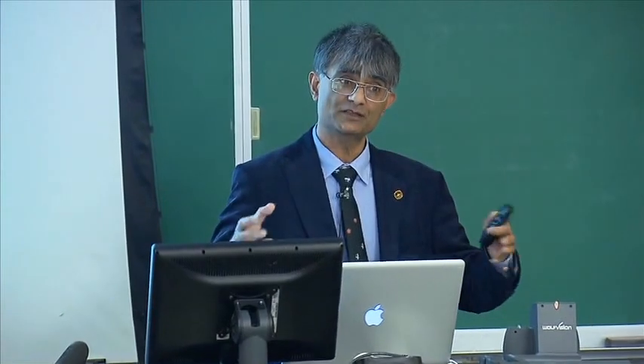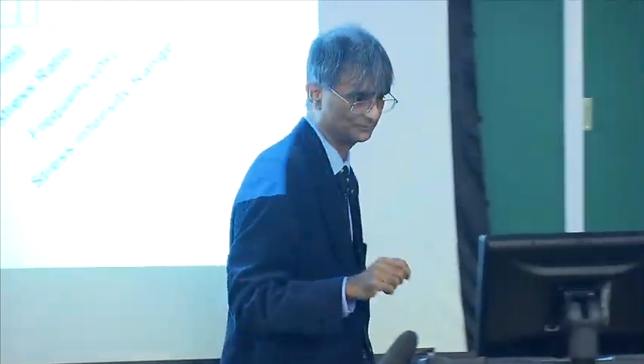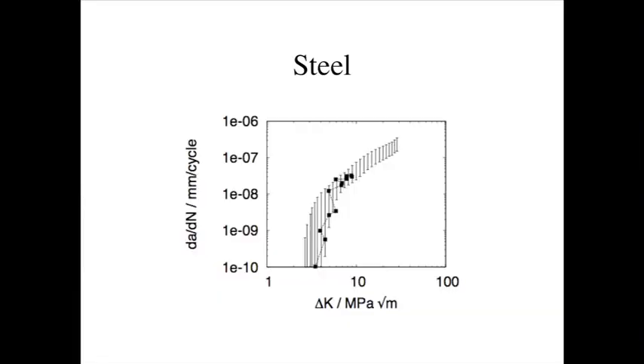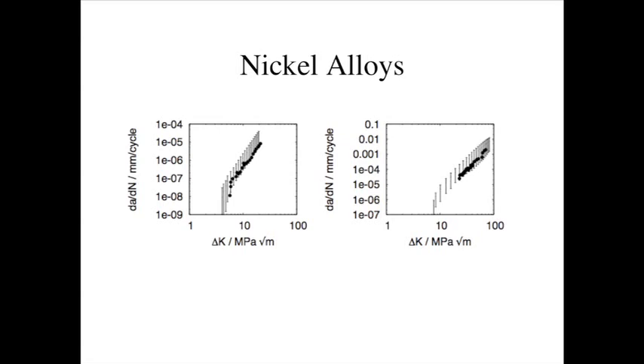Because you could argue that the composition and the heat treatment are embedded in these variables, which are strength, elongation, and so forth. So this is the model being tested on unseen data for steel. This is the threshold fatigue crack growth intensity, and this is the Paris law region. You apply exactly the same model to a completely different alloy system. So none of these data are included in the model. This is now nickel alloys, and you can see that the predictions are pretty good.